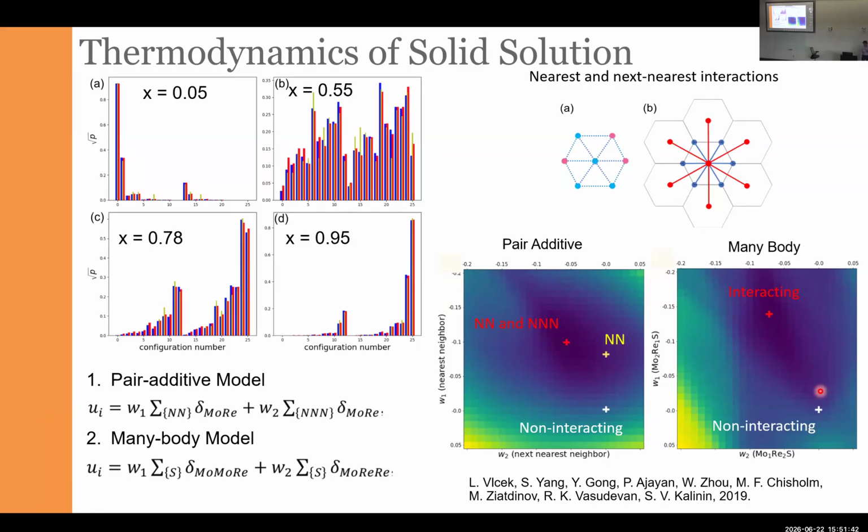So how exactly do we do that? This comes with a little bit of technical details. The question is, what do you use for comparison? Practically, it turns out that the correct way to do that is through the histogram of the possible atomic configurations. So basically, you calculate the histogram of possible neighbors in the model and in the experimental data, and then you try to find out in which part of the parameter space the distance between the histograms is smallest. There are good reasons why this is the correct metric and other metrics are not. But this is what you get as the result.